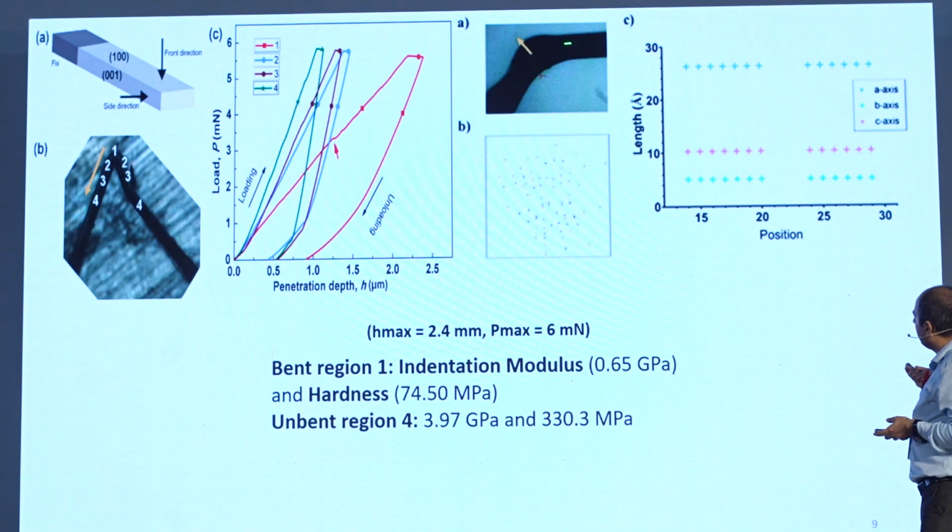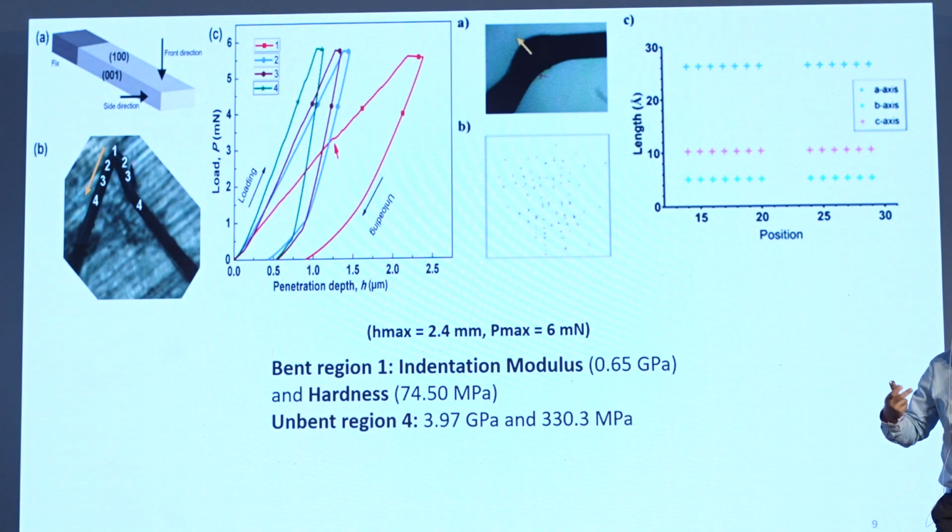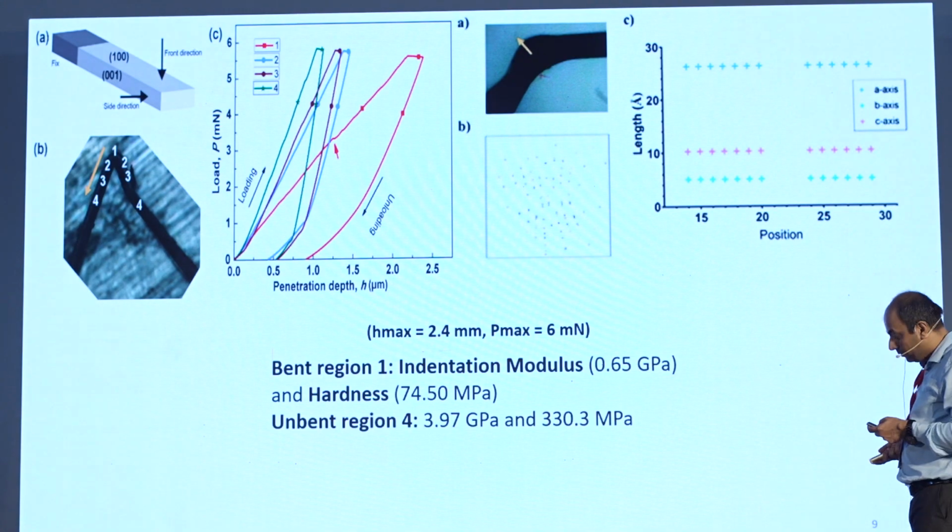And when you also have the restoration of the shape, that is also a very key feature. You see that there is some broadness in the peaks, but overall the structure remains the same. So this you can only do by very advanced experiments where you shine X-rays at every region of this crystal and see that the structural integrity is maintained.